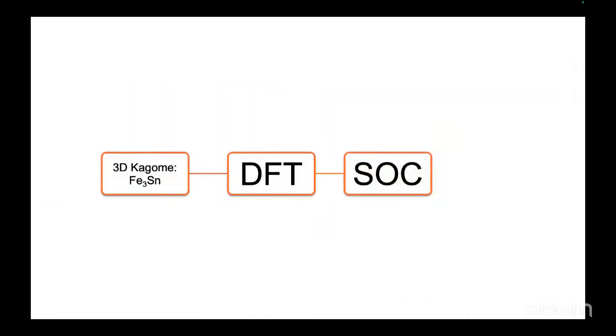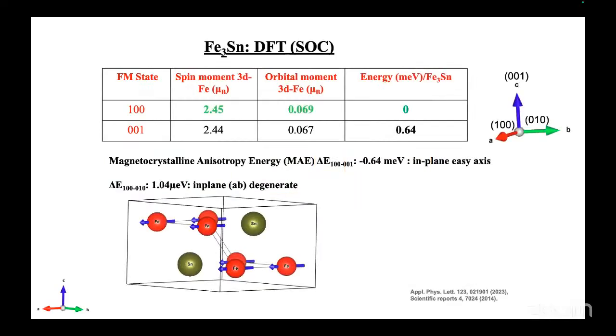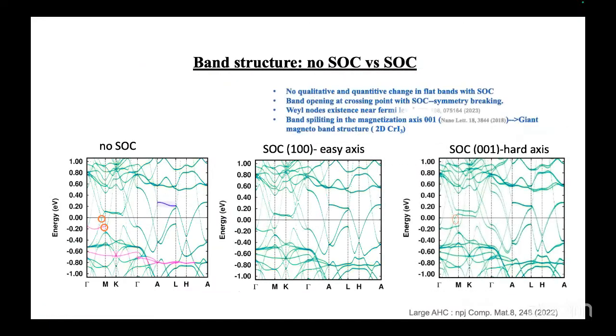Then what happens when we include spin-orbit coupling, and how does the band structure modify? Before that, we calculated the magnetic anisotropy, where we get a very high in-plane magnetic anisotropy of about -0.6 in plane. Along the plane, the system is nearly degenerate because the order is in the micro-eV range, so we get a nearly degenerate in-plane spin. We have a strong in-plane anisotropy, which is in line with the experimentally reported results in the literature. Going to the band structure, how it modifies along the in-plane and the out-of-plane.